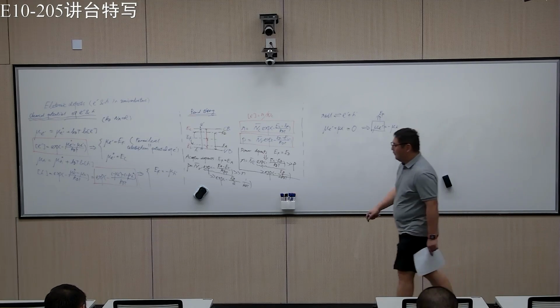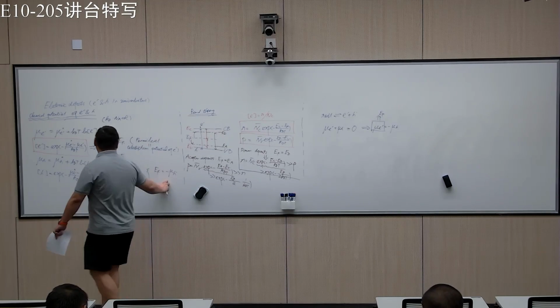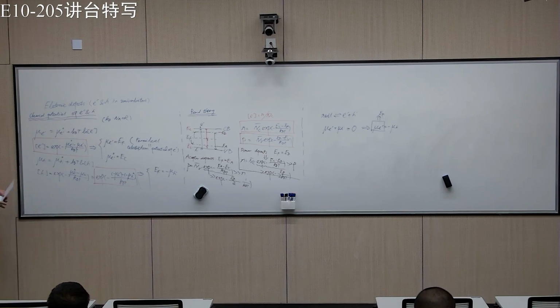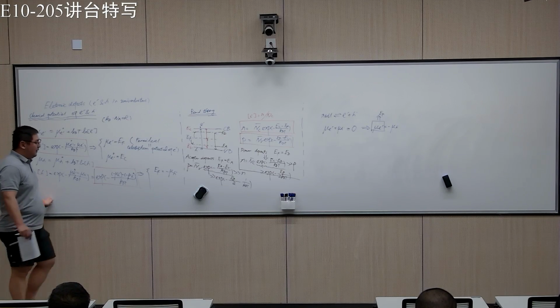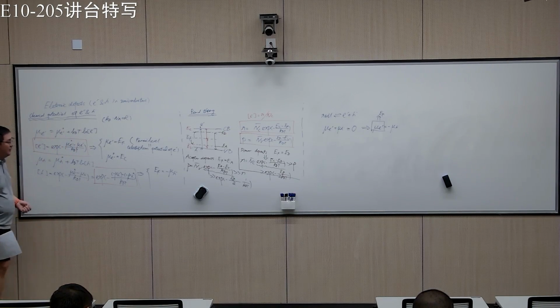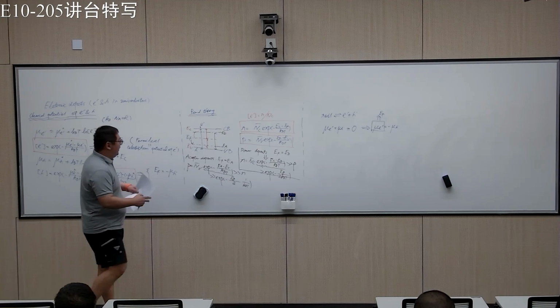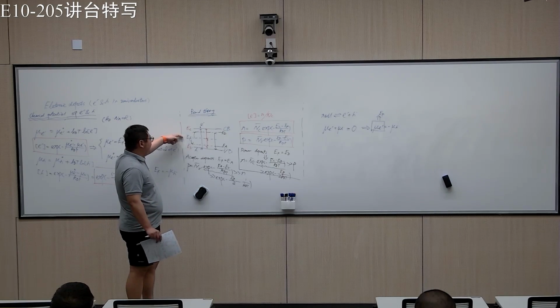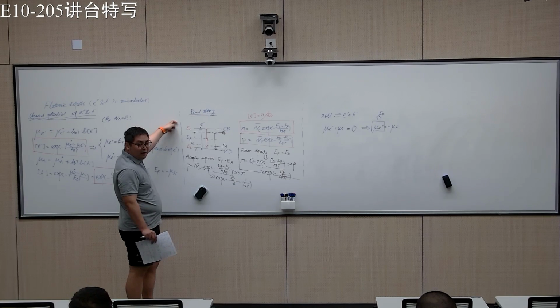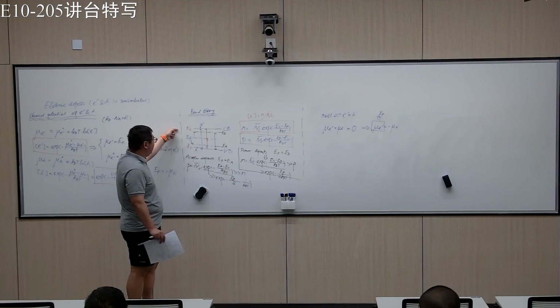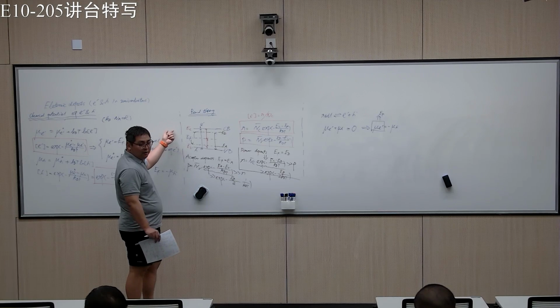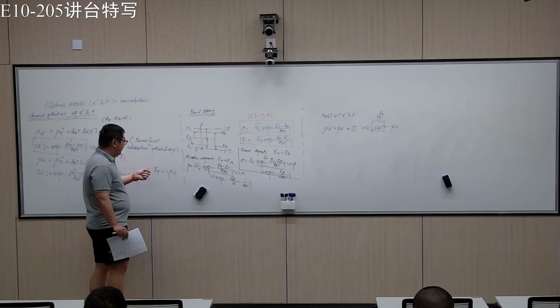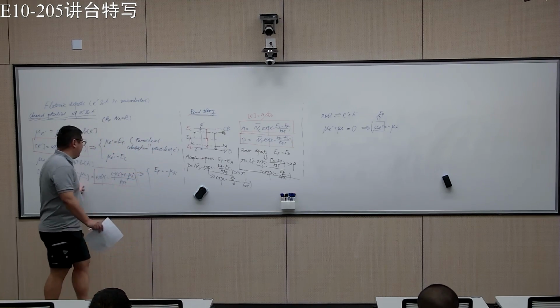This is not usually mentioned in solid-state physics because people usually just think about the Fermi level as the chemical potential of electrons. But if we follow this defect chemical reaction, we'll know more. You can also easily see in band theory that if you move up the Fermi level, you have more and more electrons, but you have fewer holes, which means the hole concentration will be lower and lower.